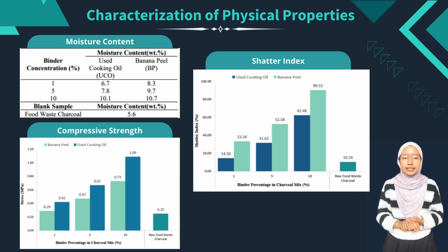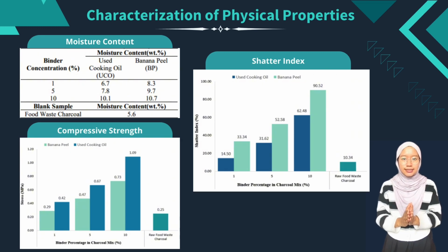For impact resistance analysis, raw food waste charcoal exhibited the lowest shattering index at 10.34%. The mixtures containing various proportions of binders exhibited higher shattering indices due to potential variations in binder distribution and also binding strength. The briquette sample with 1% used cooking oil shows the highest shattering index at 14.5%, which exceeds the shattering index of the other mixed briquette samples.